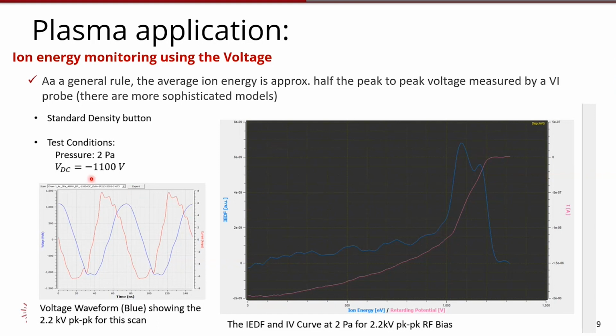So, VDC will give you an idea about the average energy, but with this data, you can actually gain a lot more. So I only mentioned a simple model here, but you can go a lot deeper and get a lot more information. I actually have clients who've gotten the full ion energy distribution function from the VI data, which is a lot more informative. But again, if you have the VDC as an output on your tool, then that is definitely informative of the ion energies. But be careful at low frequencies.